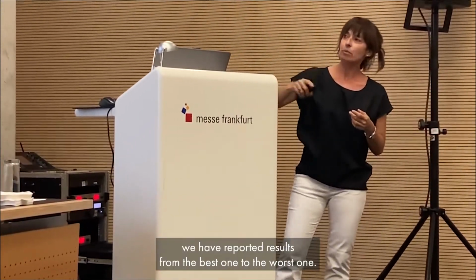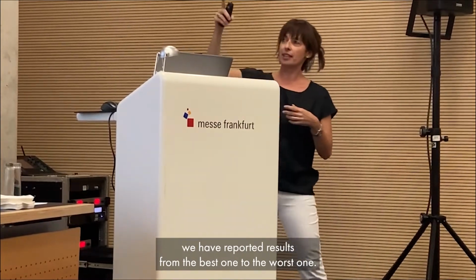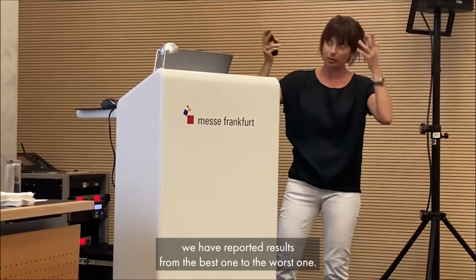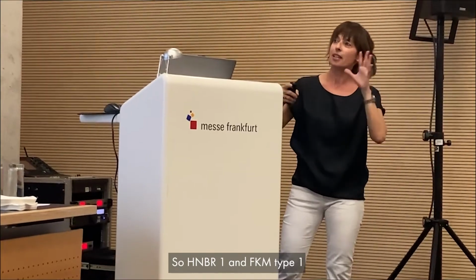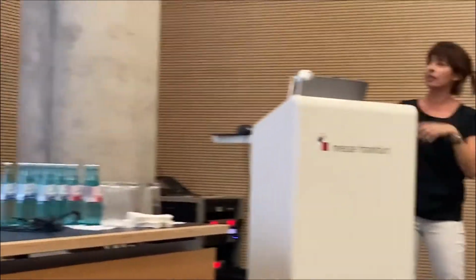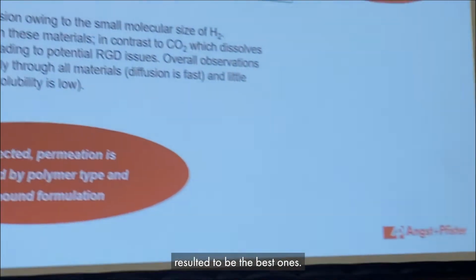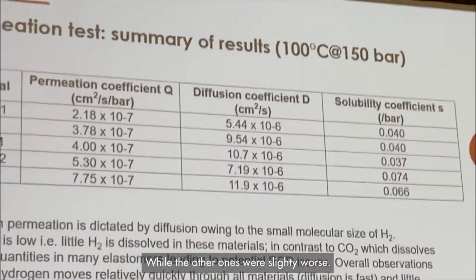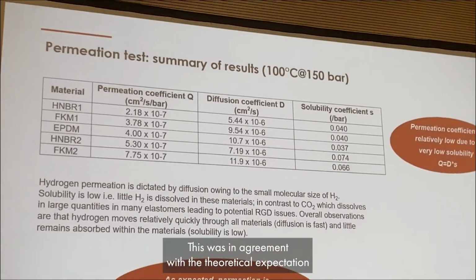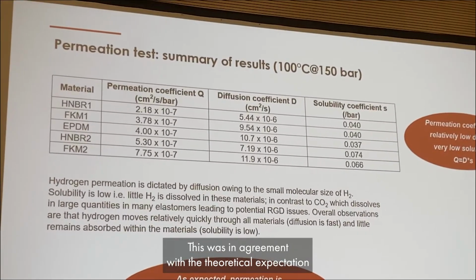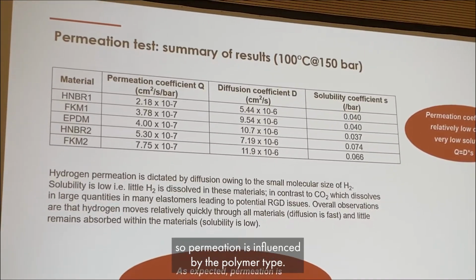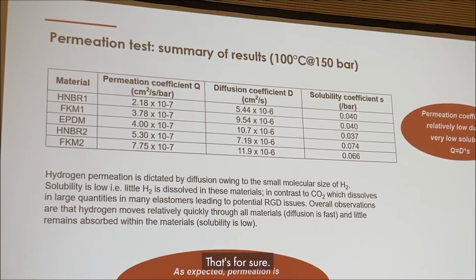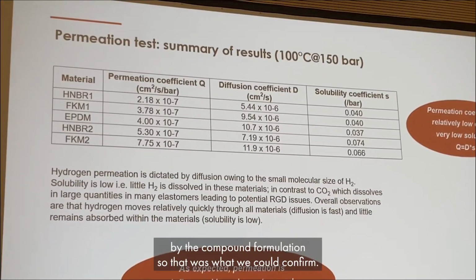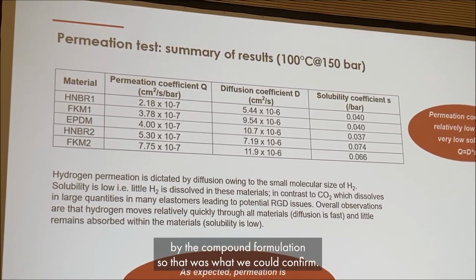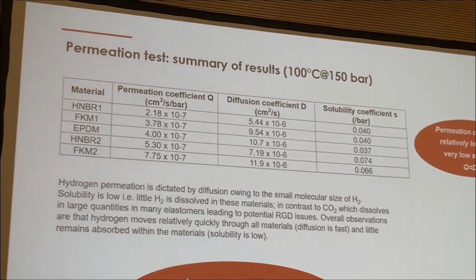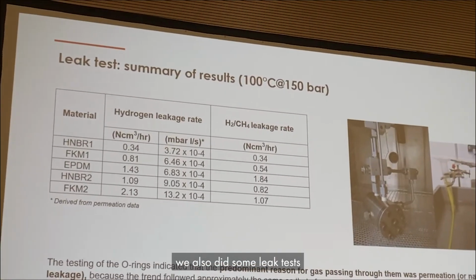As you can see, we have reported the results from the best one to the worst one. HNBR1 and FKM type 1 resulted to be the best ones, where the others were slightly worse. This was perfectly in agreement with the theoretical expectations. So permeation is influenced by the polymer type, that's for sure, and that's influenced by the compound formulation. So that was what we could confirm. At the same time, in parallel, we did run also some leak tests.